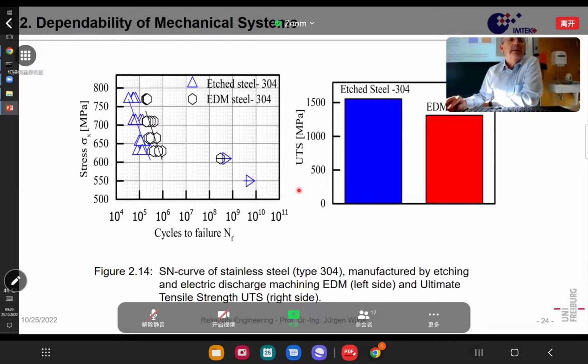In that way, you can clearly see for these two steels this curve. That point here was 550. I think that was not tested to the end. We just stopped because almost 10 to the power of 10 cycles takes a long time. Our machinery could test so many cycles because the frequency of testing was high. In a big part, you have a frequency of a hertz or 0.1 hertz. But at 1 hertz, you can hardly test 10 to the power of 9 cycles. But at 500 hertz, it accelerates it significantly.